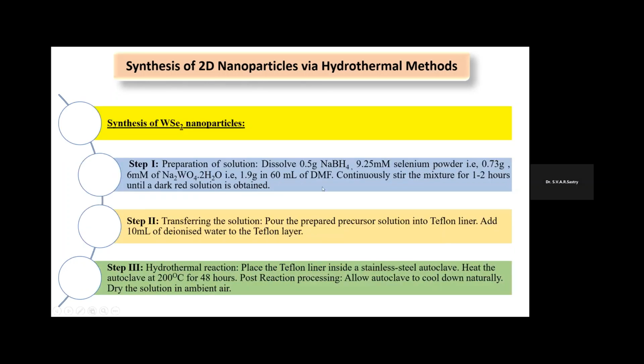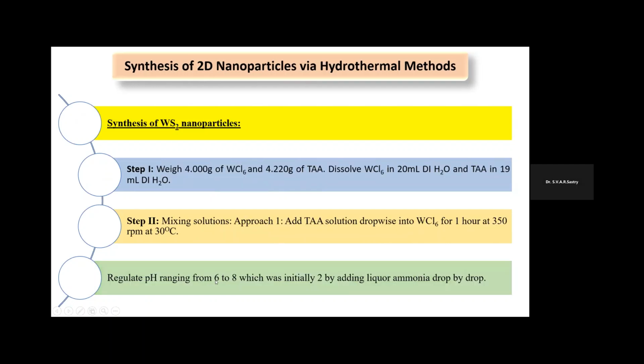So coming to WSe2 nanoparticles, here we have used NaBH4 as a precursor. Then we used selenium powder and this chemical, and then transferred to the autoclave, which was Teflon lined. Then there was the hydrothermal reaction. The temperature of the hydrothermal reaction in this case was 200 degrees Celsius, and the time was 48 hours.